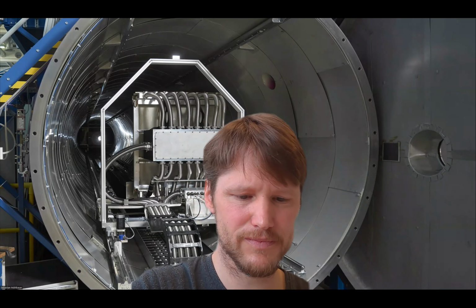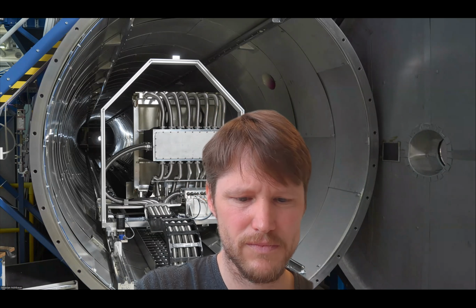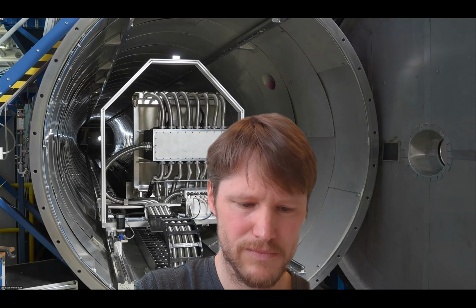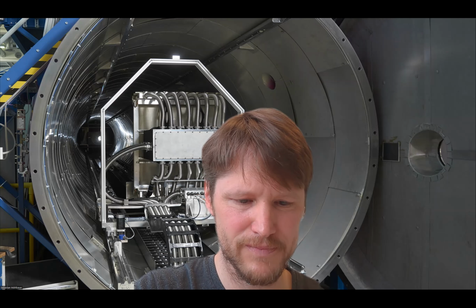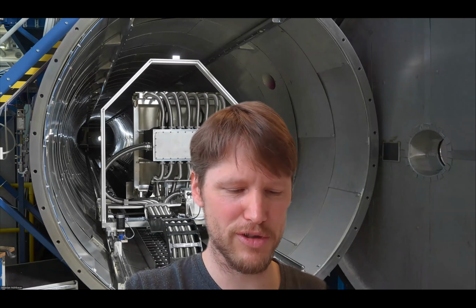Okay, do you really see the atomic structure in small angle scattering? That depends on the wavelength that we are actually using, and also if we are out of the superconducting behavior. Okay. What else do you see in your background apart from the structure? We can see what we call spurious effects, depending on the sample as well. We can observe scattering from the background, and obviously we can see the unscattered neutrons, so that's why we need a beam stop. We need to block some of those unscattered neutrons. Yeah, you need to catch these, otherwise they just burn a hole into your detector.